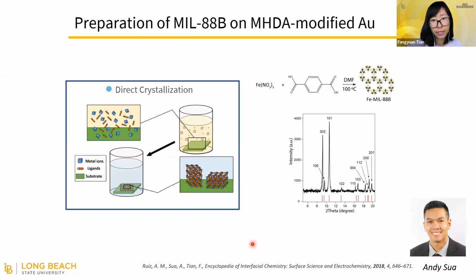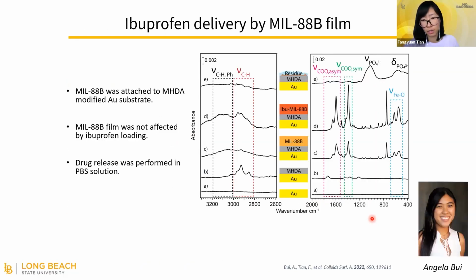My graduate student, Andy, started this project, and we tried different methods of building this crystal directly on top of the surface. We found that the direct crystallization method is the best way of loading different amounts of MIL-88B on top. Then we confirmed the structure of our MIL-88B, which is the right crystal structure. Angela worked in my lab as an undergrad student and continued this project. She connected those MIL-88B crystals to the modified gold surface and tested how much ibuprofen can be loaded there. We found that after we use a PBS solution, the majority of the MIL-88B will be gone.